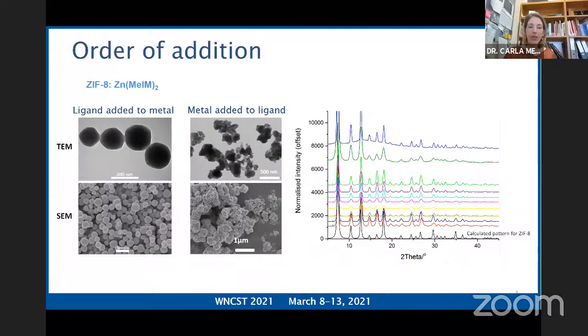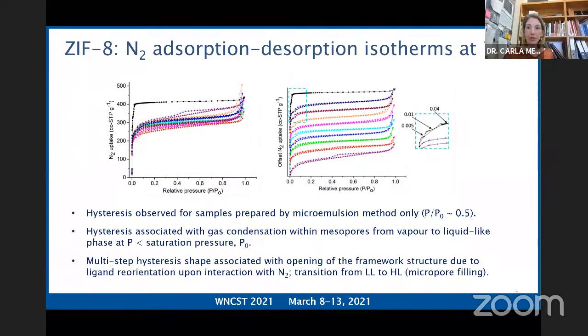But we can go a wee bit further then and compare the gas adsorption properties. So what you're looking at here is the N2 adsorption-desorption isotherms for a variety of the ZIF-8 nanocrystals. In black here, this is the isotherm for ZIF-8 that was produced using a conventional solvothermal synthesis. So this is conventional bulk ZIF-8 macroscopic crystals, and these are all the nanocrystals prepared using a variety of synthetic conditions using the microemulsion method.